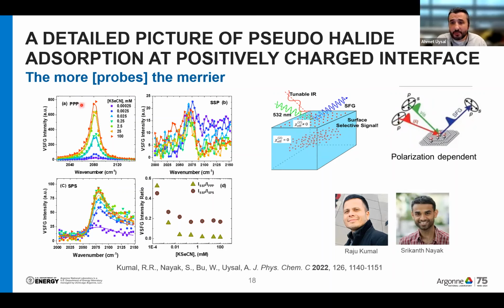By choosing different polarization combinations, we can resolve how the orientation of these thiocyanate molecules is changing at the interface. For example, in this PPP polarization mode, the signal is very strong and keeps increasing with the increasing bulk concentration. But with SSP polarization, we pretty much don't get any signal. And SPS is giving a stronger signal compared to SSP, but weaker than PPP. Its trend as a function of bulk concentration is also different, demonstrating that the orientation of these molecules is changing as a function of the bulk concentration.